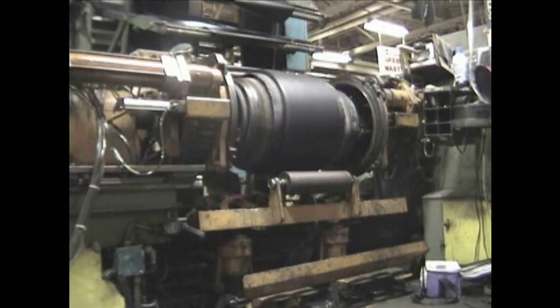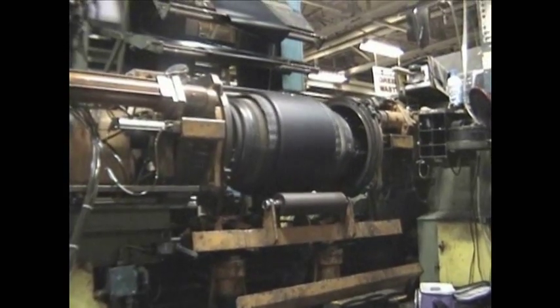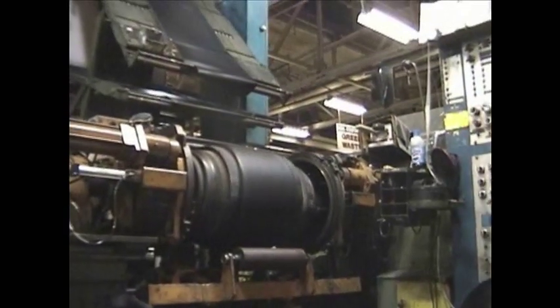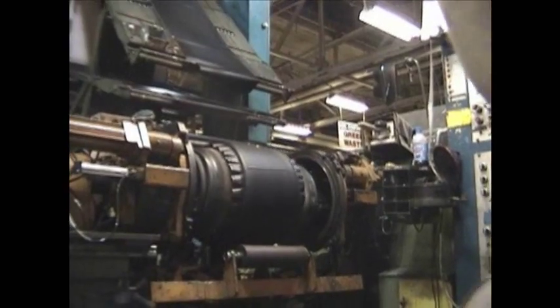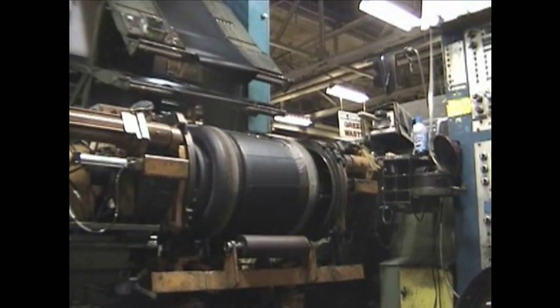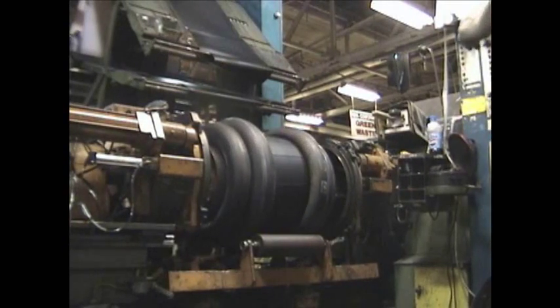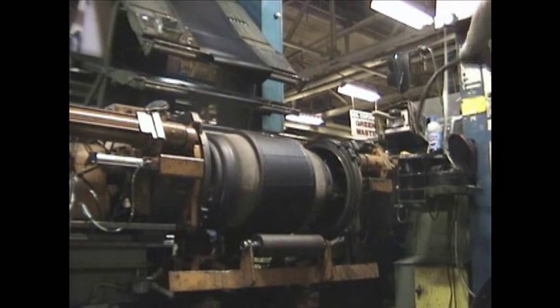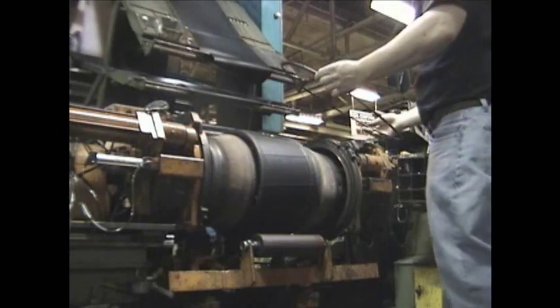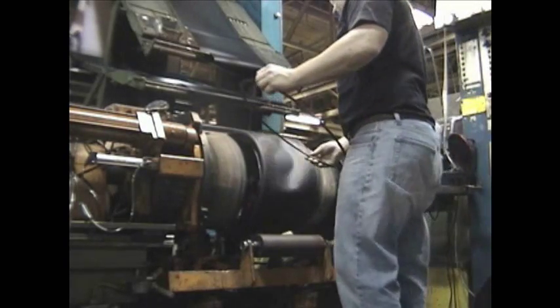Now the beads are on and the machine puffs a little bit. Now it's going to roll. From the back there's a roller pressing all those layers together. This is all raw rubber. So it pushes together to make it stick. The bladders puff out and it closes to roll the rubber over the bead. Now the bead is encased on the carcass and we get back to the beginning putting the bead on for the next step.